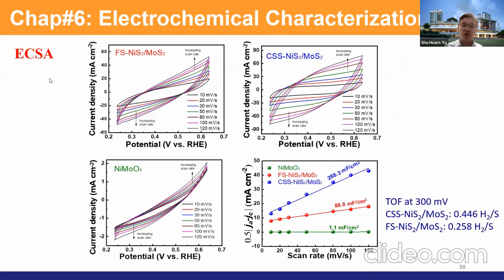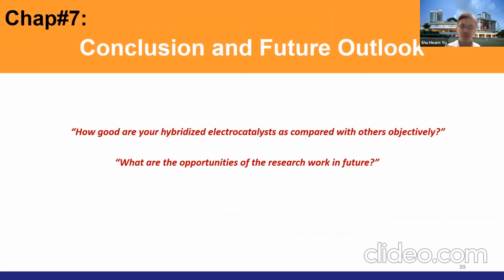And after that, we also tried to find out the surface area of the material, and we find that the controlled surface sulfurized catalyst indeed has a higher electrochemical surface area compared to the fully sulfurized nickel sulfide and molybdenum disulfide. And it also has a better turnover frequency as compared to the fully sulfurized sample. So what I want to emphasize here is that controlled surface sulfurization is a very new method. There's extra room for you to explore, not only in the hydrogen evolution reaction, maybe in the ORR, oxygen reduction reaction, or oxidation reactions, or carbon dioxide reactions. It could also be useful.